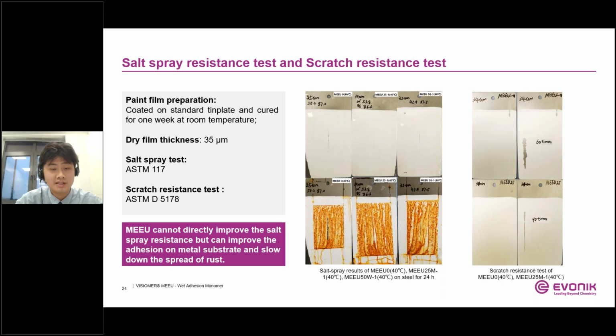And the scratch resistance of industrial paints was tested based on the ASTM D5178 standard. As the picture on the right side shows, the scratch resistance has also been improved after adding MEU. Not only has the number of scratch resistance increased, but the area of damage to the paint film has also decreased, which demonstrates improved adhesion to the metal substrate. So the result shows MEU cannot directly improve the salt spray resistance, but can improve the adhesion on metal substrate and slow down the spread of rust.